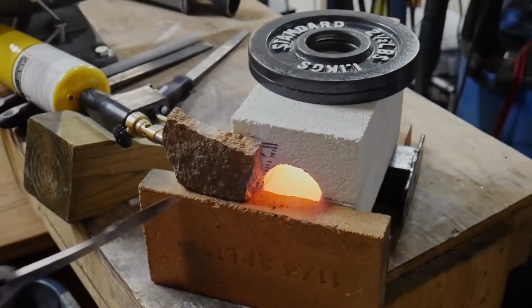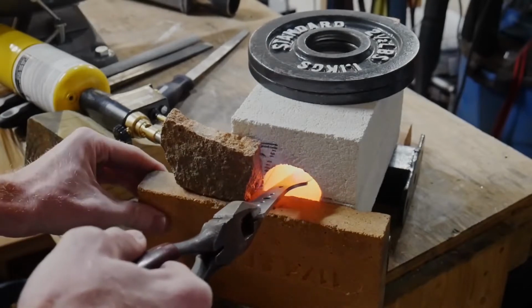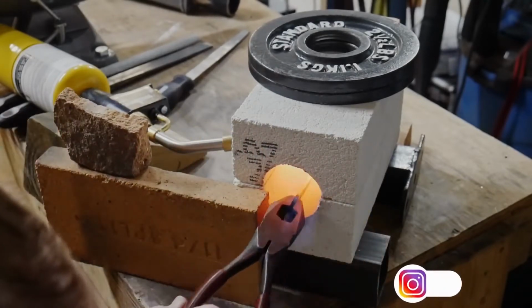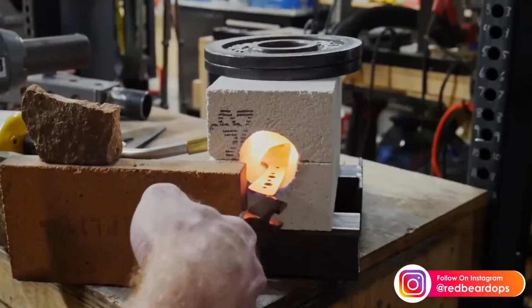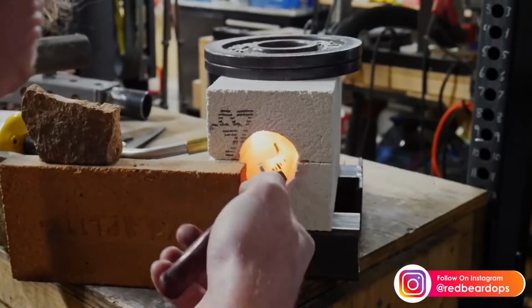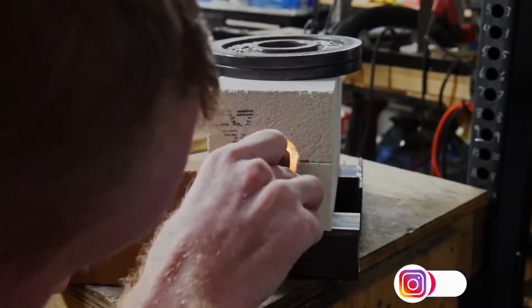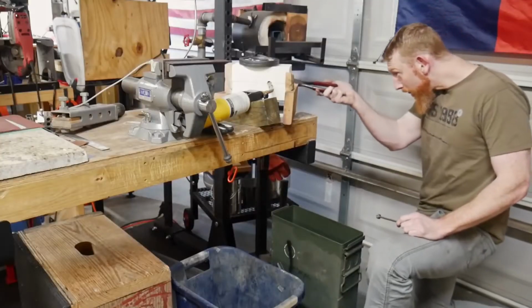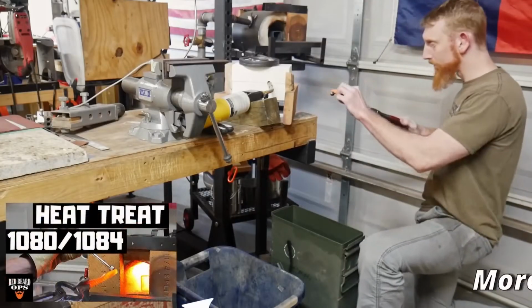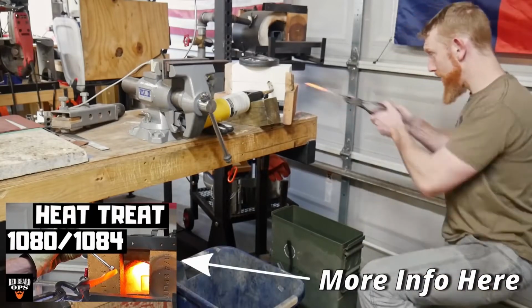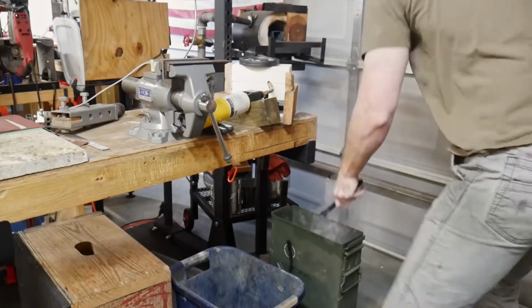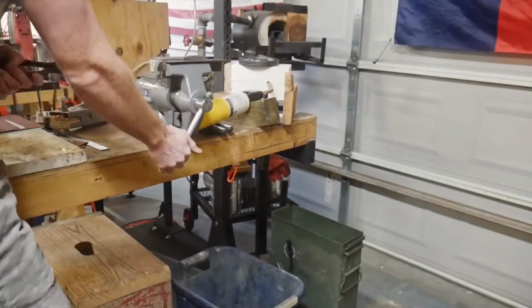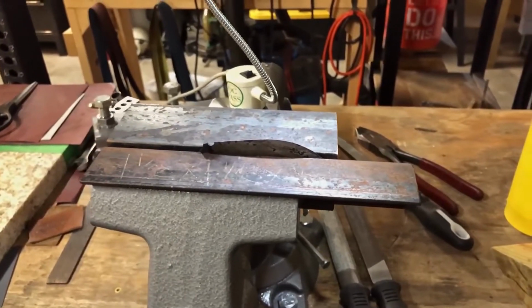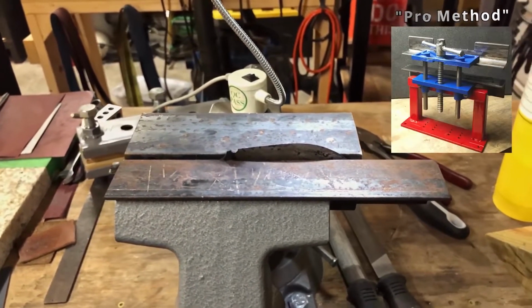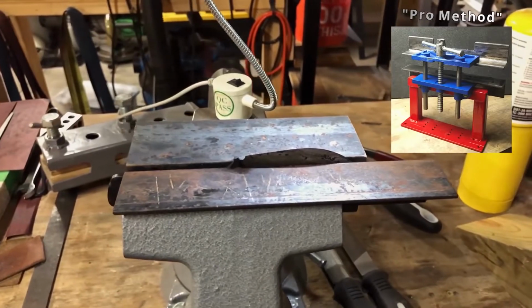I used another fire brick, a hard fire brick on the front, just to allow it to heat up a little faster, and then I removed it so I can fit the knife into the chamber. To stick with the cheap nature of this knife build, I just used a pair of pliers to hold on to the tang of the knife. I'll get the knife up to a non-magnetic heat and then target around 100 to 200 degrees higher than that non-magnetic temperature before quenching it in oil. You can use canola oil, but in this case I use Parks 50. I then took 2 pieces of angle iron and my vise and clamped the knife down after a 4 to 5 second quench.